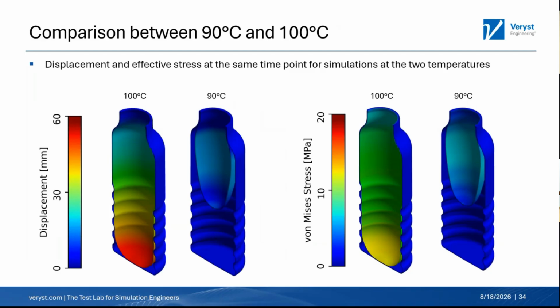And as I kind of foreshadowed at the beginning, we did this testing at 2 different temperatures. So what we've done here is we've tried to look at the difference in the material response at the same time of loading for those 2 different temperatures. So if we run this at, say, 100 C at the same time, you can see that we've almost filled the bottle. So that one on the left shows that we're almost completely full there. We can see the stress as well as the displacement, right? We're getting higher stresses, we're getting more displacement. We almost filled the bottle, we're going to get there. But if we look at the 90 C one, at that same pressure and at that same time, you can see that we've only expanded the blank a little bit.